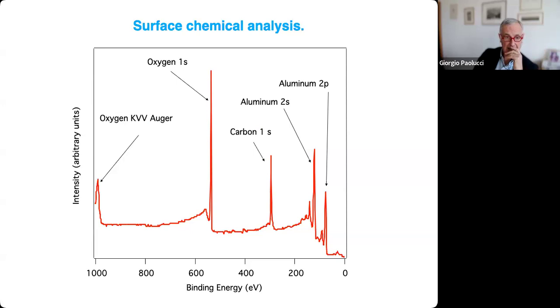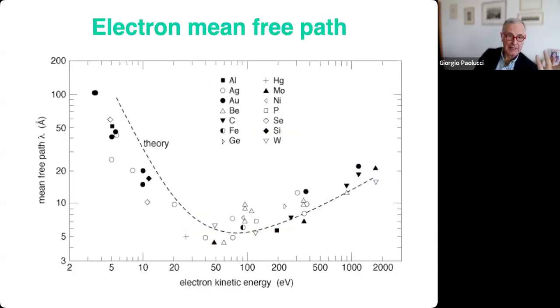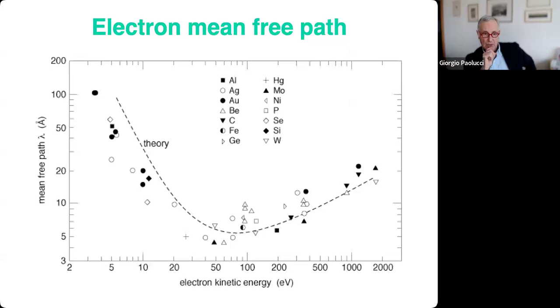Because we are looking at electrons whose kinetic energy is of the order of 100 or a few hundreds of electron volts, one has to keep in mind that the mean free path of electrons depends on the kinetic energy, and it is very little at low kinetic energy. It is of the order of a few angstroms. And because of that, this spectroscopy is very good if you want to look at the surface of your sample. So you're looking just at a few atomic layers of your sample.